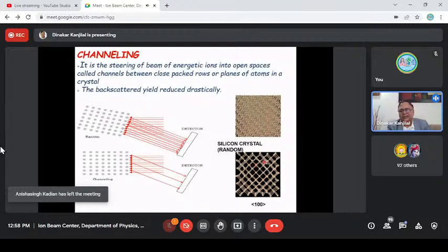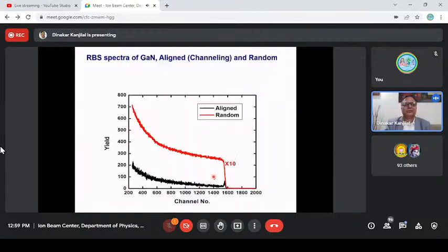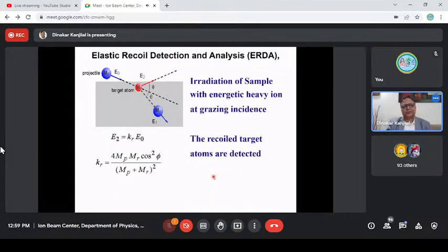There is no other method; X-ray will never show you, because X-ray works by 2d sin theta equals n lambda. So X-ray doesn't see each atom, actually it is a K-space representation of the spectrum. So even if you remove the top 10,000 atoms, the X-ray spectrum will be the same. Only intensity may slightly fall depending on how many you are removing.